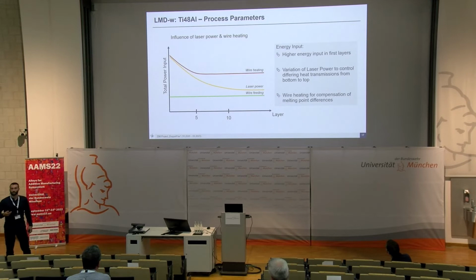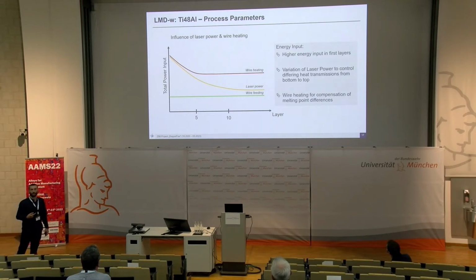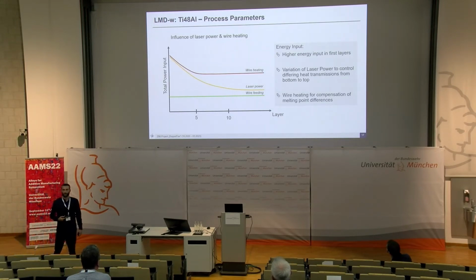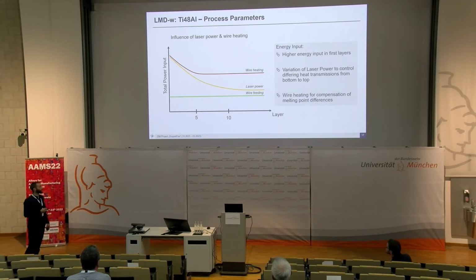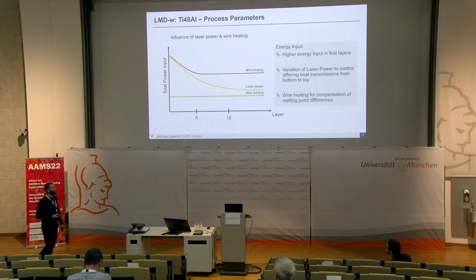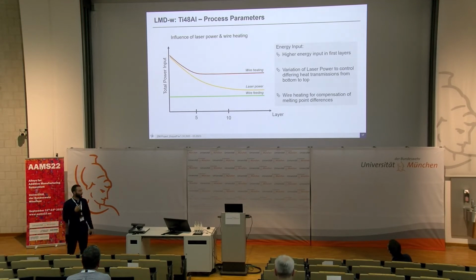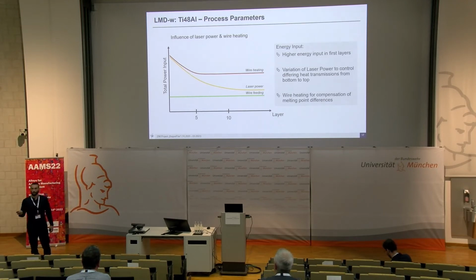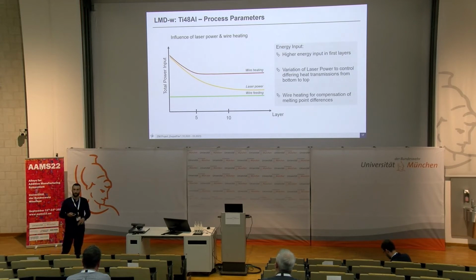When we look at the whole process, from the first layer to the last layer, we need to manage our energy input. In the first layers, we need a higher energy input to get the process rolling. But then we need to vary the laser power down to control the heat transmission from the bottom to the top. With every layer, the bed is getting hotter, so we have to regulate the laser power. Also, the wire heating is controlled. The wire heating is furthermore really important for the compensation of the melting point differences. We have aluminium with around a 660-degree melting point and titanium with 1,600 degrees. So we have a 1,000-degree difference between those two wires.